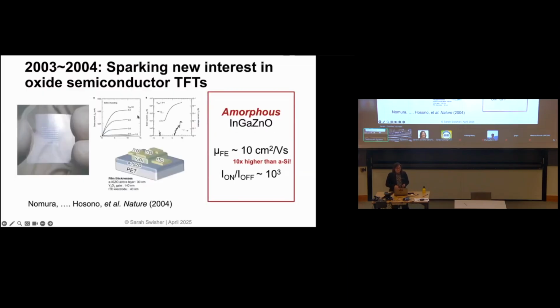So about a year later, they did the same thing, but instead of heating it up and making that crystalline film, they made an amorphous film, meaning the atoms are not in that long range periodic order. They're just sort of randomly arranged relative to one another. And usually that means that electrons can't move through that material very well. They get stuck. But in this case, this material has some really unique properties, and the electron transport through the material did get worse, but it was still 10 times higher than amorphous silicon.